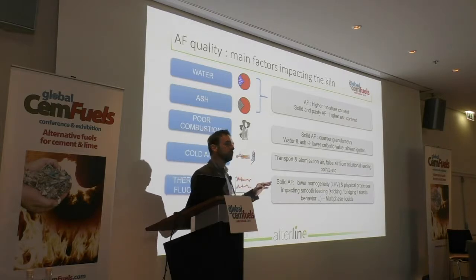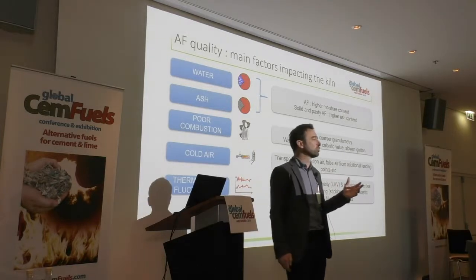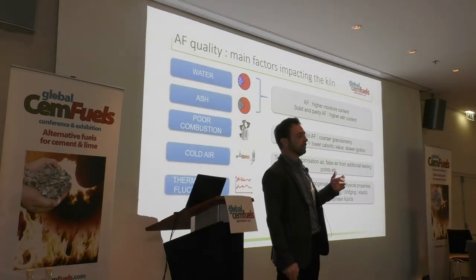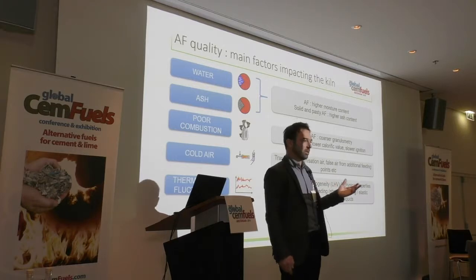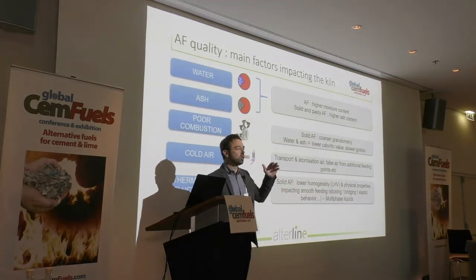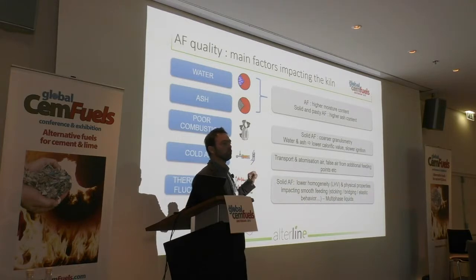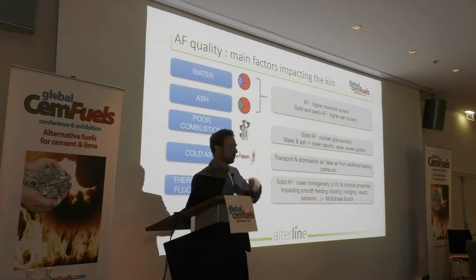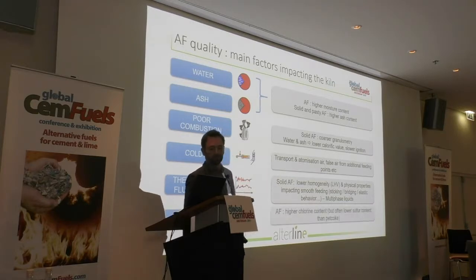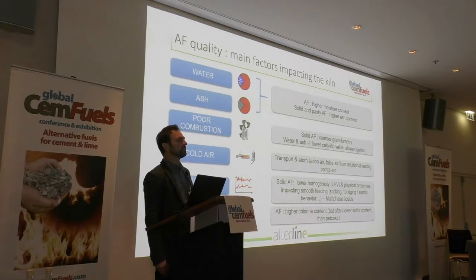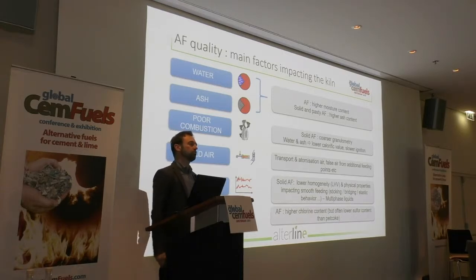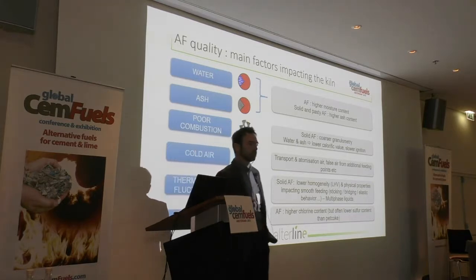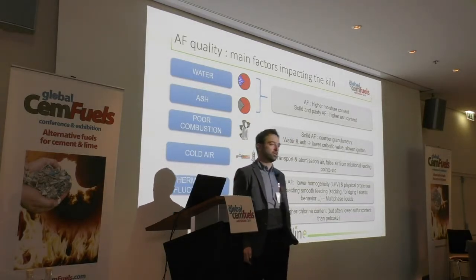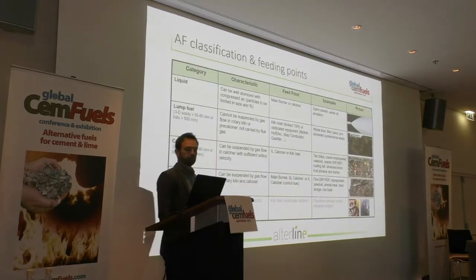You will have fluctuation in both calorific value, but probably also in the throughput. It's not only small fluctuation, it also includes the stop of the feeding because of bridging, because of clogging of the pipe, because we will come back on it. And then the circulating elements, so mainly the chlorine, since if you use petcoke, and especially high sulfur petcoke, probably you will decrease the sulfur input of the kiln.